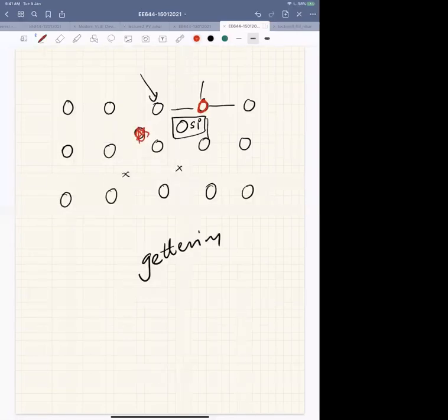Right. So what happens is this arsenic and silicon form a cluster, and these clusters move away from the active area. So you will have this cluster formation also. They are inactive clusters, because they are not in the lattice site. But this arsenic can react with the silicon interstitial and form some kind of arsenic-silicon cluster, but still they are inactive. They do not participate in the bonding process.